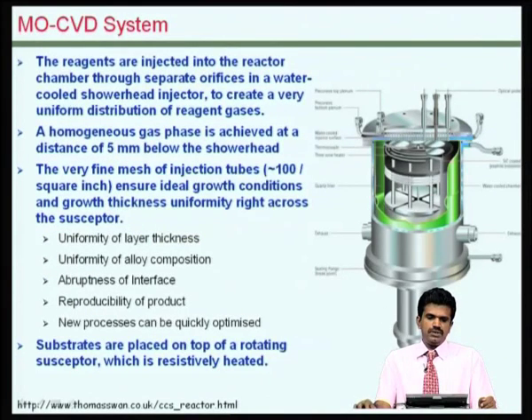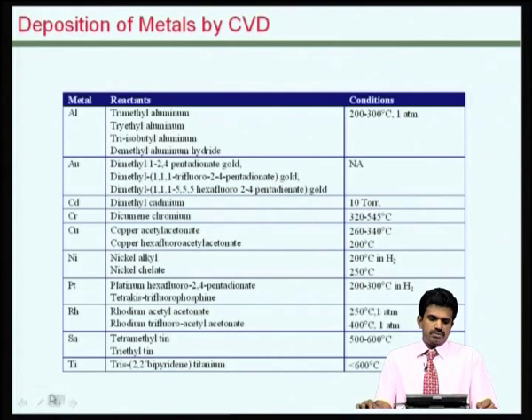In a typical MO-CVD system, various reagents are injected into this chamber, and just like in any other CVD scheme, we make the chemical reaction happen, and we also do some kind of rotation and things like that, so that uniformity and good control of the film deposition can be obtained by this approach. As you could see from the list here, many metallic films can be formed based on their organic precursors that are used in these CVD systems.